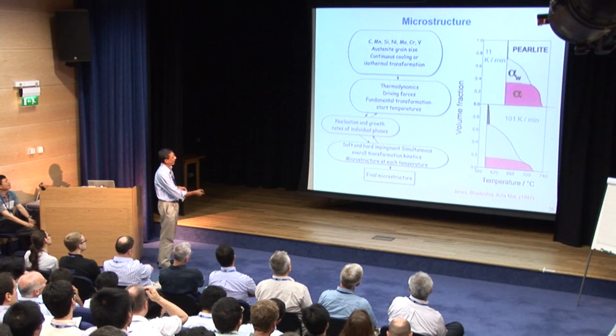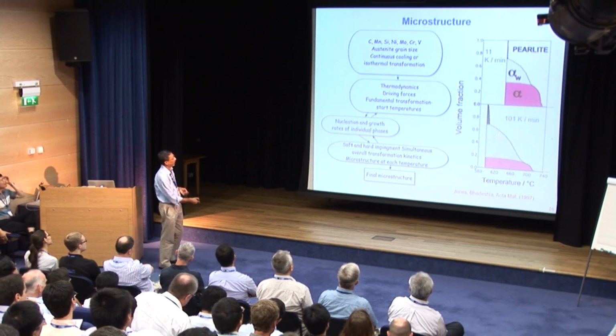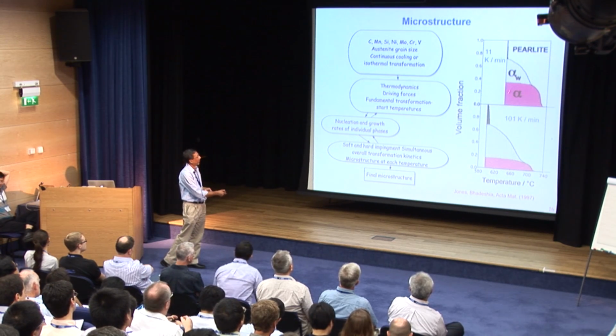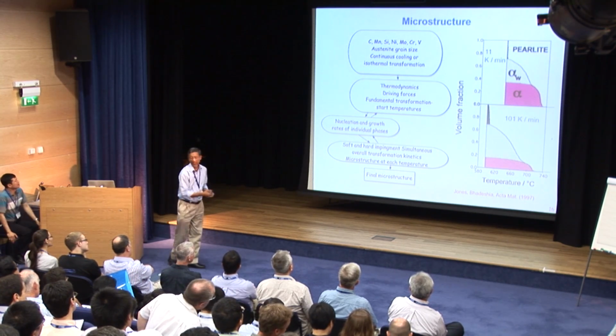We did this, and what we found was the most important thing is nothing worked. Nothing worked until we put in a stored energy of about minus 200 joules per mole, all right? About 3.7 joules per gram for steel. And then, of course, we were able to predict the effect of cooling rate, and we expect the grain boundary ferrite, the Widmanstatten ferrite, and pearlite.